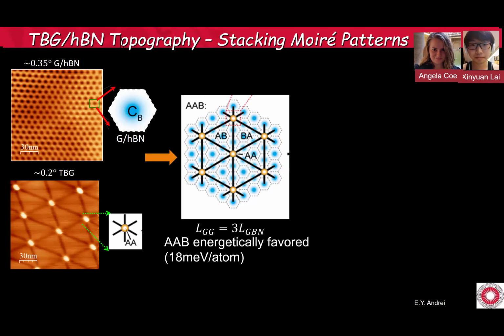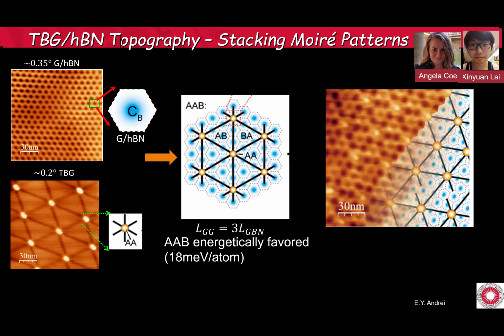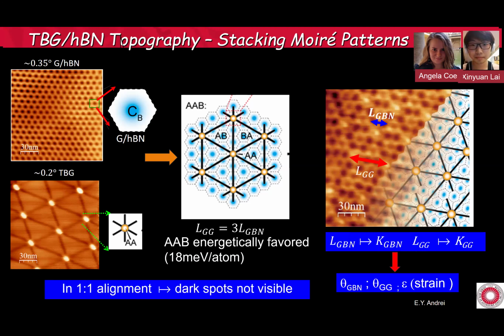For example, when you have LGG is 3 times LGBN, you're going to get something like this. These are the AA regions, and these are the GBN region. And this is an actual sample. So what we have to do to find the lattice constant of GG is to measure the distance between the bright regions here. And if we measure the distance between the dark regions, we get the lattice constant of GBN. So once we have that, we can go to reciprocal space and we find KGBN and KGG. We can immediately calculate the twist angle and we can get the strain out of it. I'm going to show you one example of how we do this.